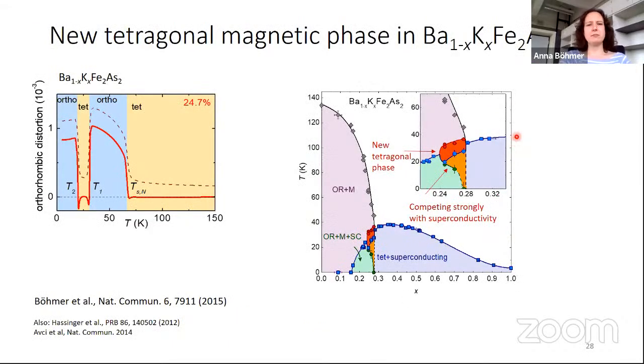A surprising discovery we made is that we learned something about a new phase, and that's this little red region here. When we did these measurements, we found that the orthorhombic distortion on cooling comes up and then disappears and then comes back. And that was our discovery of a new little phase pocket in our phase diagram here, which was also seen by others. But to us, seeing this curve was a real surprise and told us about the power of this technique.